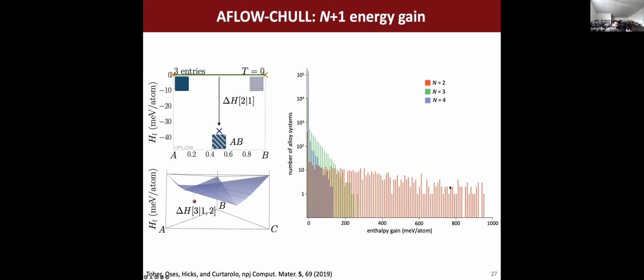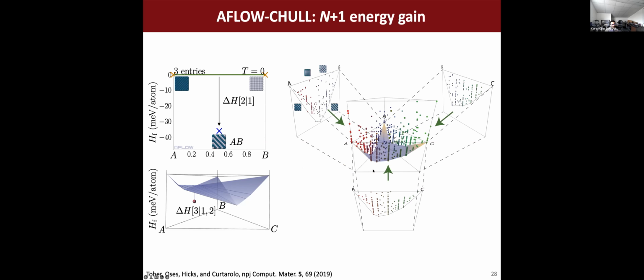And what you can see here is that as we increase the dimensionality, as we go from binaries to ternaries, not only does the enthalpy gain decrease, but there are fewer compounds that show any enthalpy gain. And what this derives from is an important concept of this increasing competition as we increase the dimensionality of the system.